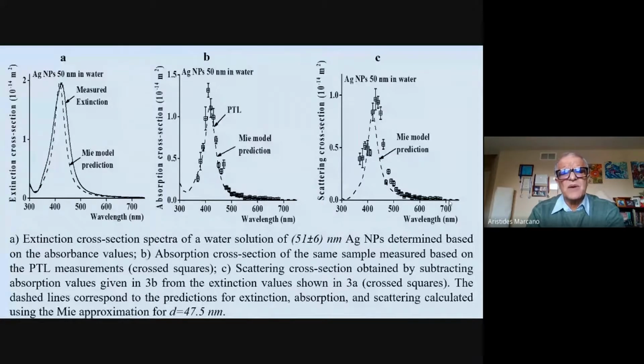Here's another experiment we did for smaller nanoparticles. Now the scattering is a lot less than the thermal lensing, and you can see that it has similar numbers, but you can see the comparison between the Mie predictions and the measurements is really good.